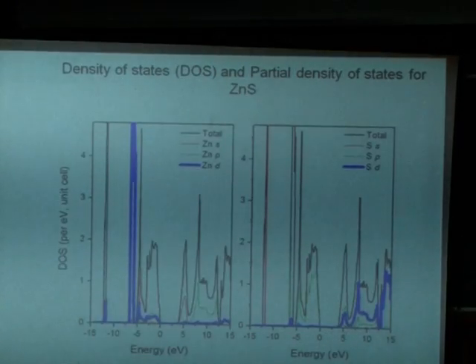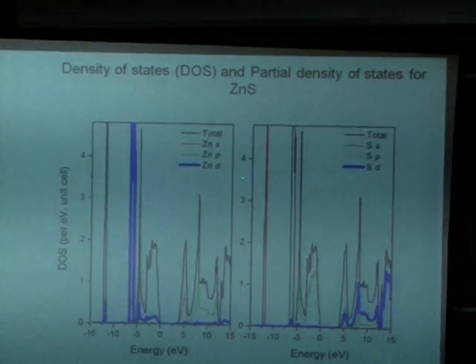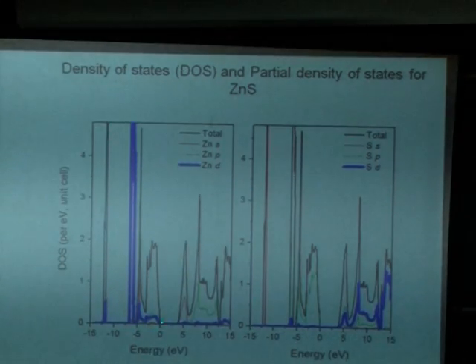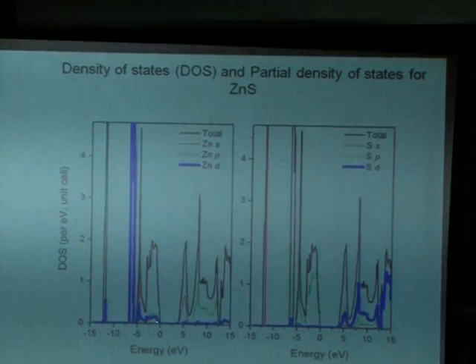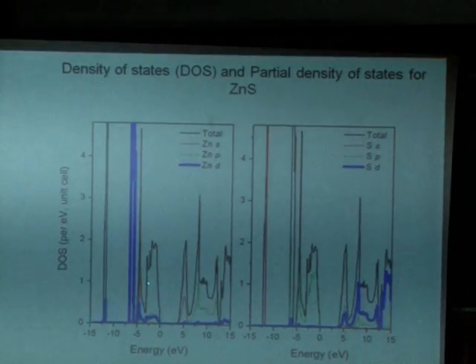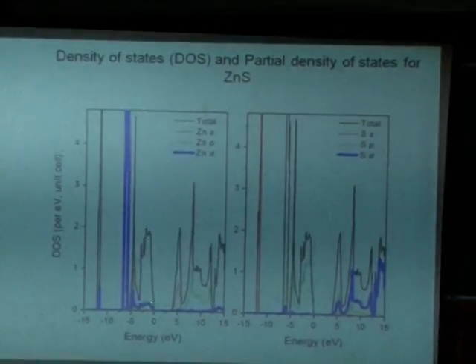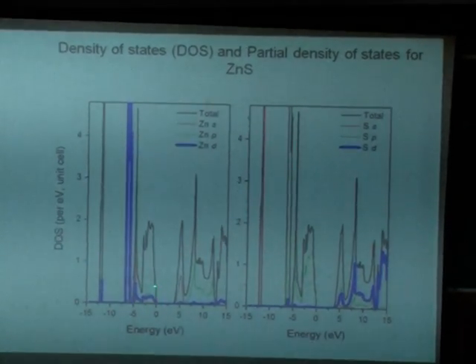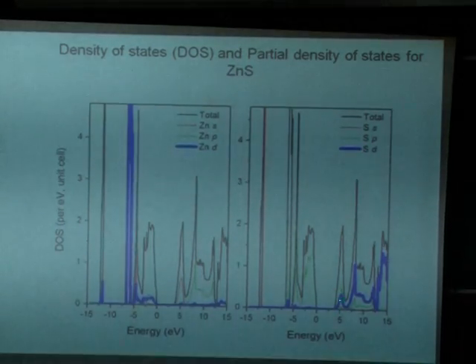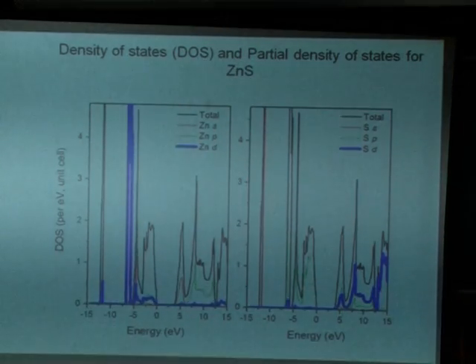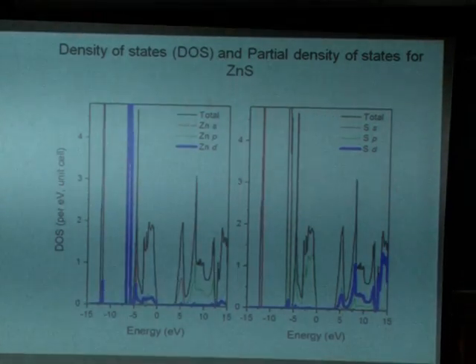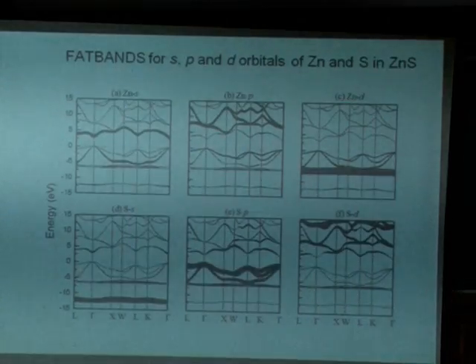Then we tried to understand where the model is going wrong, and we found that the zinc D states contribute quite a bit towards the top of the valence band. The black is the density of states, and the blue is the contribution from zinc D states. Likewise, sulfur D states contribute quite a bit to the bottom of the conduction band, which is this one. Which told us that sp3 is not a good basis, we must bring in the D states also. So we bring in the sp and D states. Now it becomes even bigger.